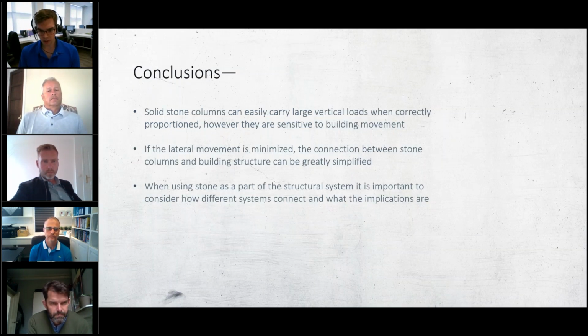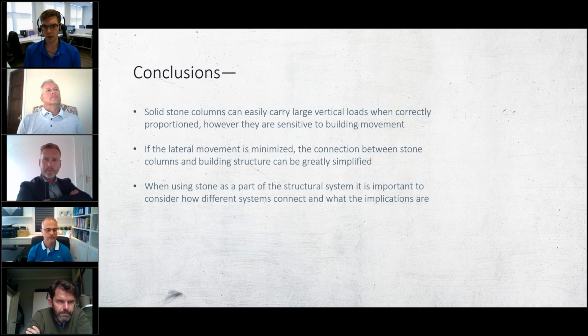In conclusion, despite the large loads that pass through these columns, they were all properly proportioned to avoid buckling. The challenge was actually in connecting the steel system to the stone columns so as to ensure compatibility. The project needed to use a fairly complicated detail, which could have been avoided if the lateral deflections had been reduced. This is why it's important to consider how structural stone will interact with other structural elements from the beginning of the design, so that the benefits of stone can be fully realized.